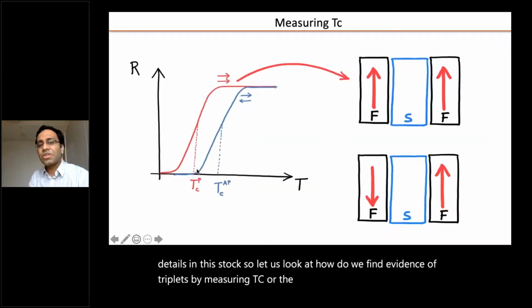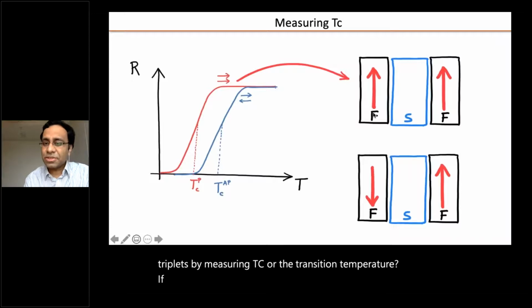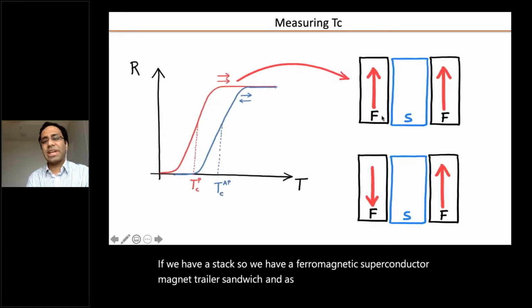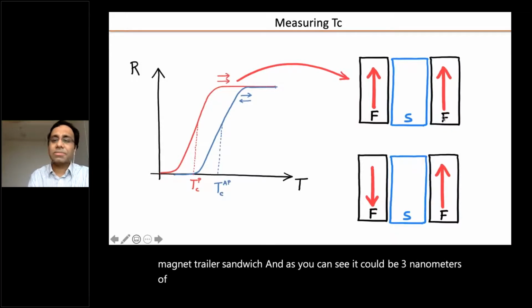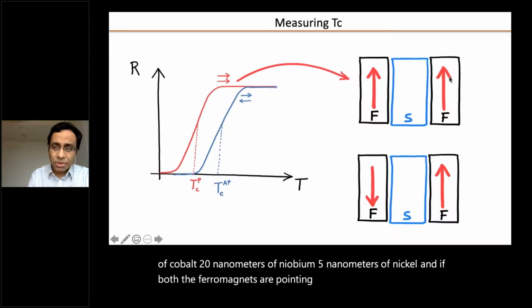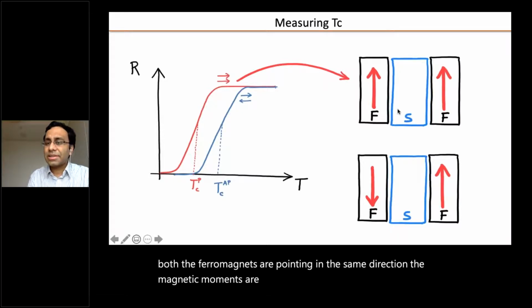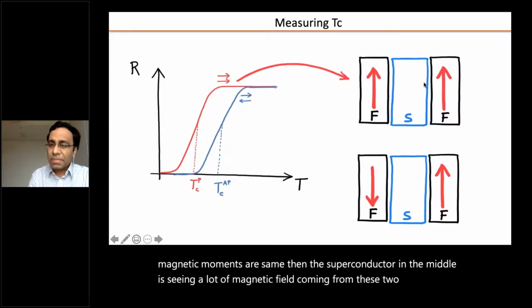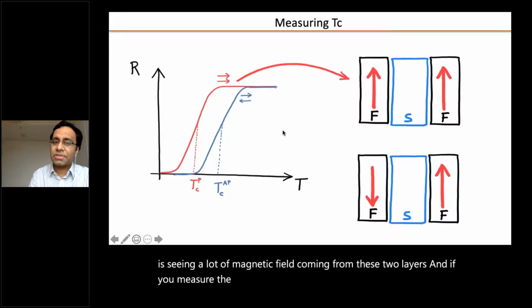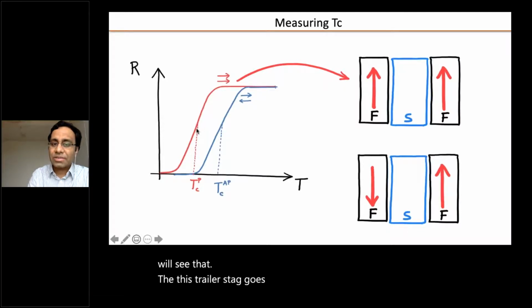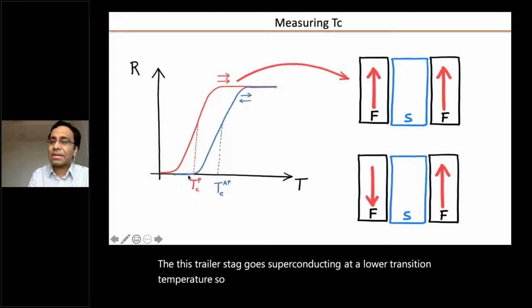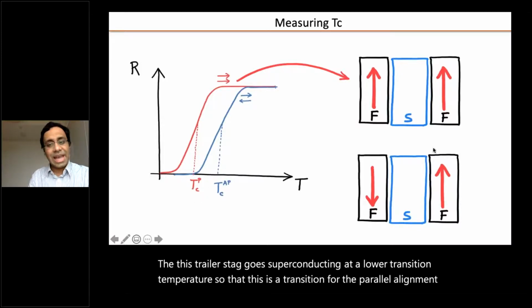If we have a stack, a ferromagnet, a superconductor, and a ferromagnet tri-layer sandwich, and as you can see, it could be 3 nanometers of cobalt, 20 nanometers of niobium, 5 nanometers of nickel. And if both the ferromagnets are pointing in the same direction, the magnetic moments are the same, then the superconductor in the middle is seeing a lot of magnetic field coming from these two layers. And if you measure the resistance versus the temperature, you will see that this tri-layer stack goes superconducting at a lower transition temperature. So this is the transition for the parallel alignment,